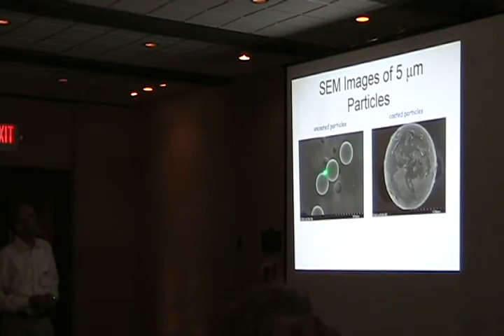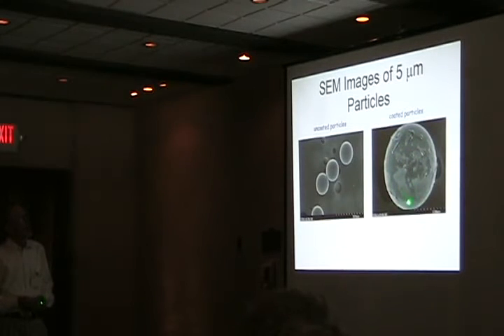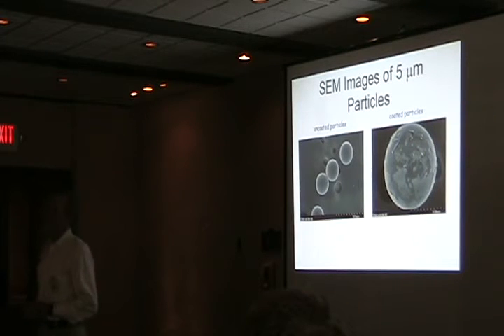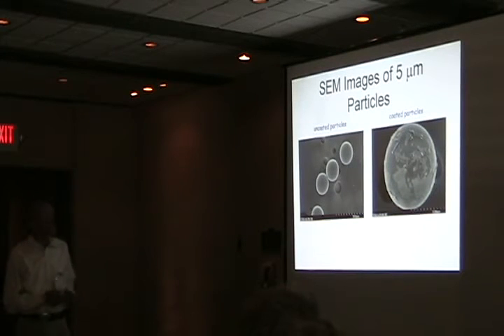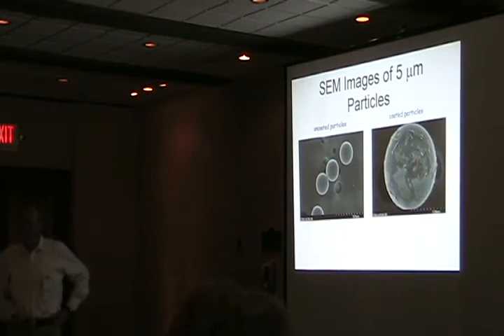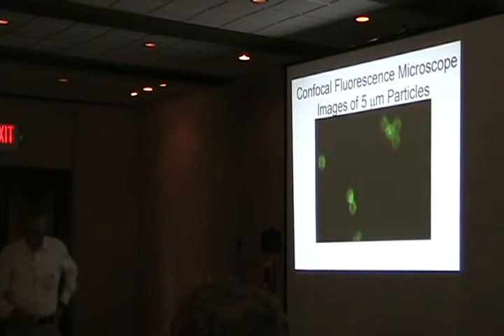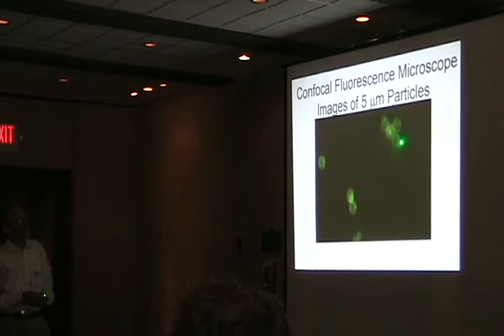This is just an SEM image of the larger particles, and you can again see it's a very ugly looking surface. Interestingly, if we look at the same kind of beads, but with the adsorbed polymer, it looks much more smooth. So there's a really big difference between these polymers that are grown on the surface and the polymers that are adsorbed as a coating on the surface. By confocal microscopy, you can see the fluorescence of the polymer very clearly. You can again see that these beads tend to stick together to some extent.